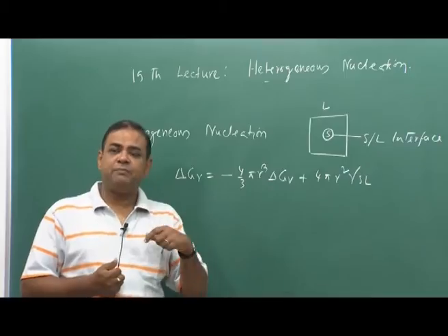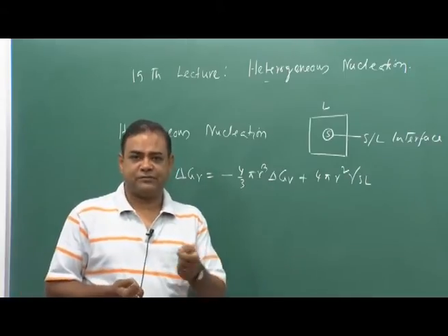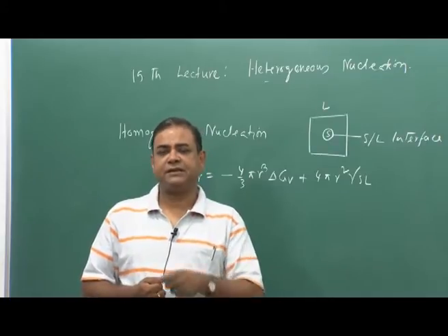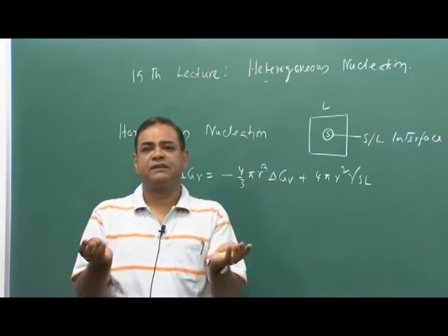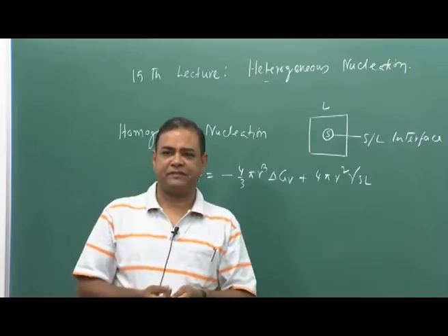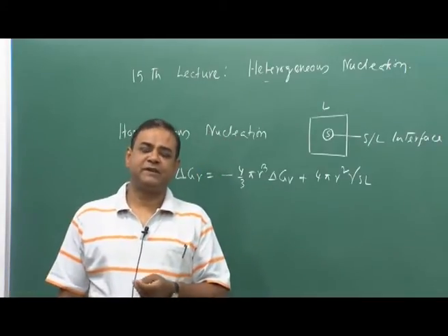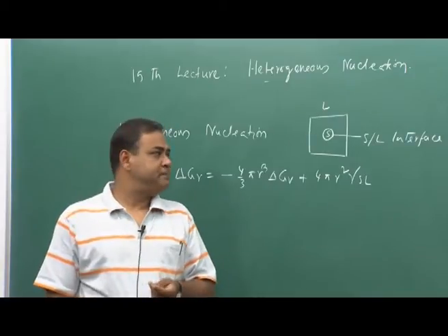So, if we do not have any mold surface assistance, the solidification mode would be a homogeneous mode, and people do levitation study. So, the liquid metal droplet is created, and the droplet does not have any mold surface, it is a containerless solidification. There we do experience homogeneous nucleation.